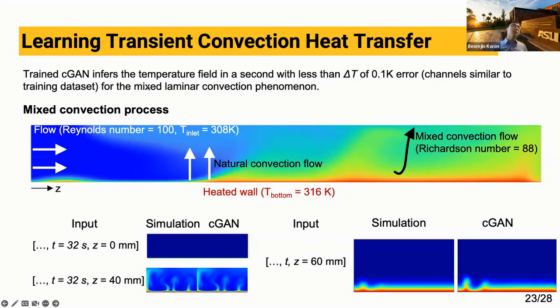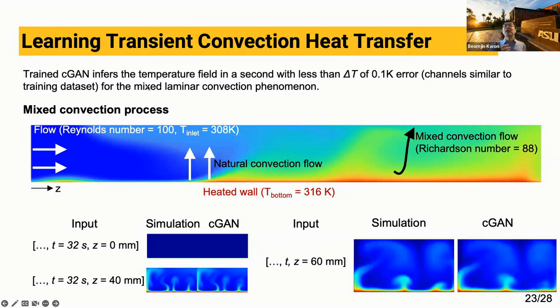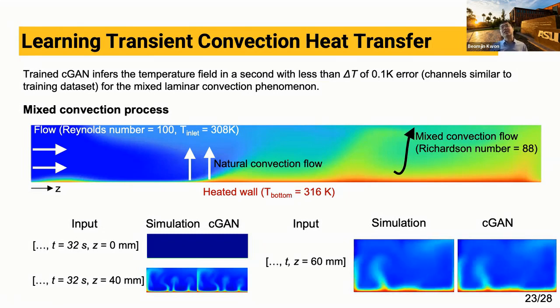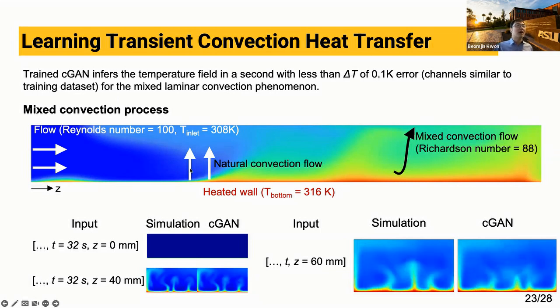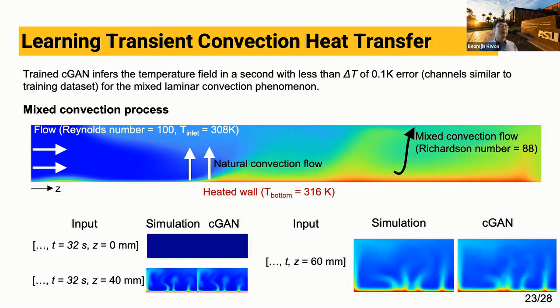So we tested this vector to image generator network for a mixed convection process. As you know, mixed convection is a very transient and highly nonlinear process, which is very difficult to express and predict using mathematical formulations. And the mixed convection actually combines natural convection and forced convection and generates uprising, circulating flow motion and also heat flow.